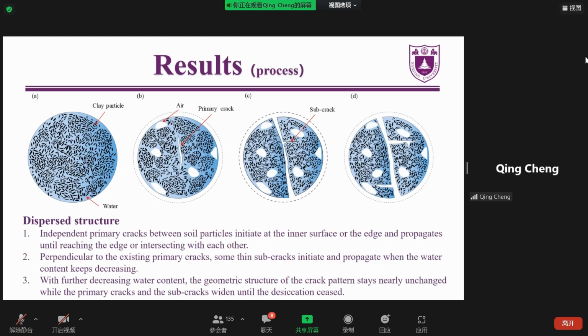Independent cracks between the soil particles initiate at the inner surface or the edge and propagate until reaching the edge or intersecting with each other. And these initial independent cracks are considered as the primary cracks. And then perpendicular to the existing primary cracks, some thin cracks initiate and propagate. These thin cracks are regarded as subcracks. Both the primary cracks and the subcracks form the geometric structure of the crack pattern.